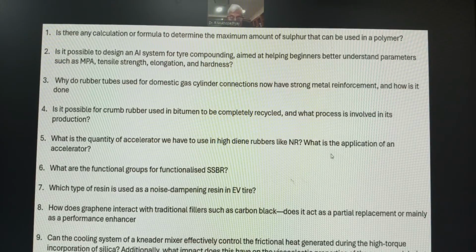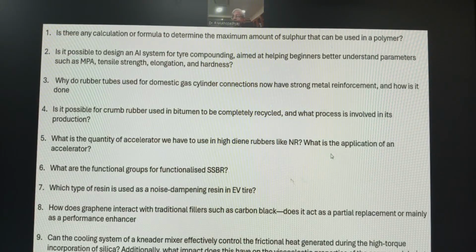If it is not a sulfonamide accelerator, especially footwear and others use MBT, MBTS, or sulfonamide plus DPG for passenger radial, depending on the case.